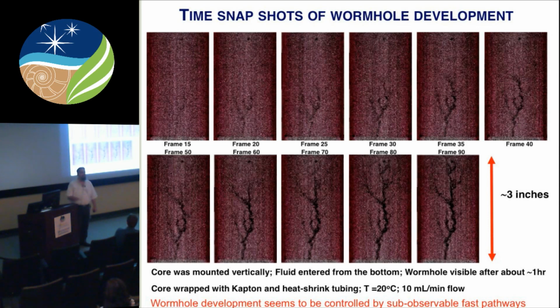This is a real limestone. And what we found, this is hydrochloric acid reacting with a limestone. Look here. By frame 15, you're already seeing this wormhole present. And instead of drilling its way, in fact, the hydration front has already gone through. It went through within the first couple minutes.